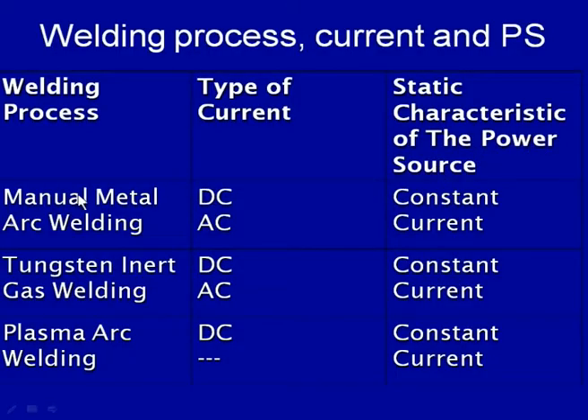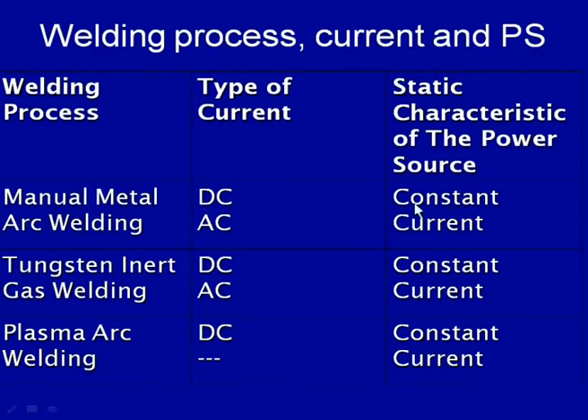Now, we will see the process wise and what type of current and what type of the power source as far as static characteristic is concerned should be selected. We know that for the manual metal arc welding process, where there is a possibility of the great arc fluctuation, we can work with both AC current or the DC current, but mainly the constant current type of the power sources are used, because the fluctuation in arc length due to the manual control helps to maintain the current largely constant when the constant current type of the power source is used, so that the heat is generated uniformly, and the uniform weld joint with the normal and the uniform properties like penetration, weld bead geometry is obtained.